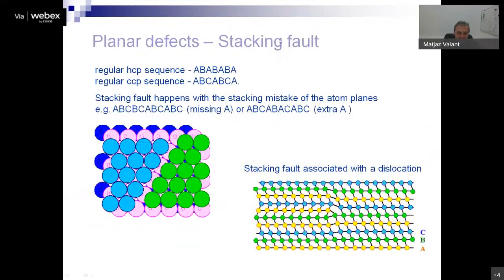Now we got stacking faults, and in metals, a lot of that is present. And the reason is we already know that the planes can stack in two different sequences, in the cubic close-packed and hexagonal close-packed system. But in some cases, the third layer can partially stack in the cubic way, and another part of the third layer can stack in the hexagonal way. So in between these domains, we would have a stacking fault.